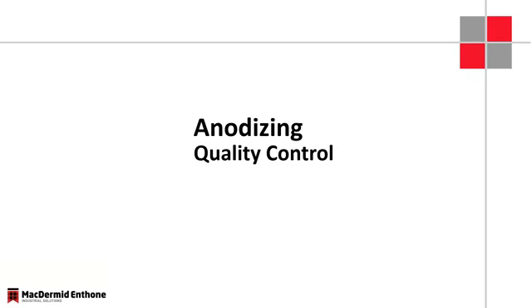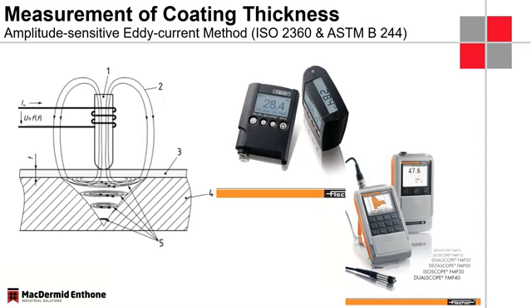So anodizing quality control, I'm going to spend a little bit of time just running through some of the things we have to do to really make sure that we meet the specifications and meet all the requirements. I think everyone knows the Eddy-current meters here. It's a non-destructive way of measuring thicknesses, and thickness is really one of the most critical parameters when we anodize. It really determines the corrosion resistance. It determines how much dye we can absorb in the surface, and it also determines how long we have to seal the surface for. If we don't control our anodizing thicknesses, if we choose the wrong time in the sealing tank, we will not achieve certain criteria to meet the specifications.